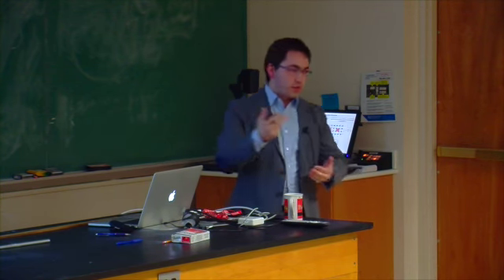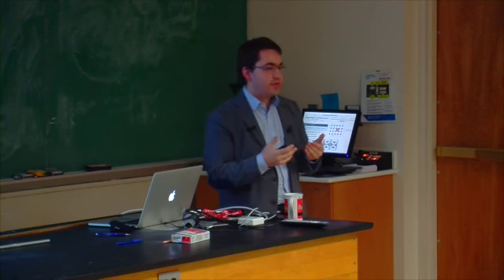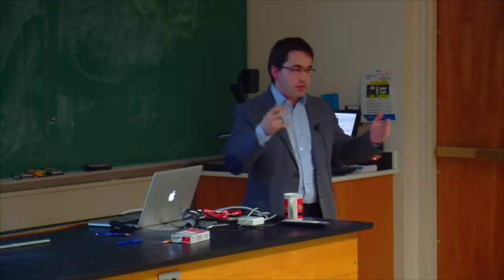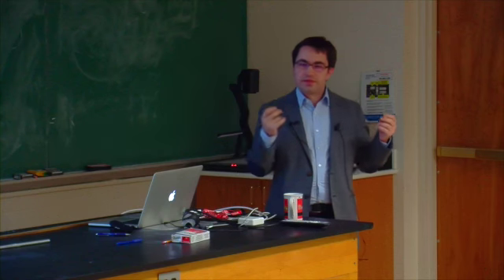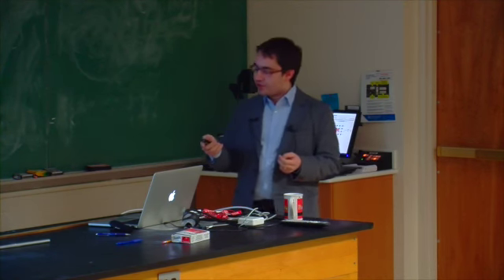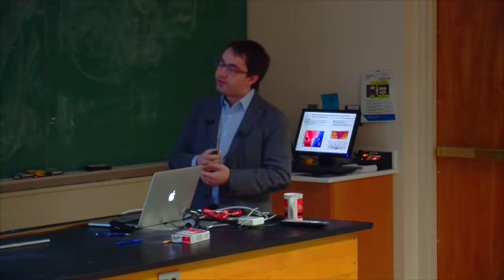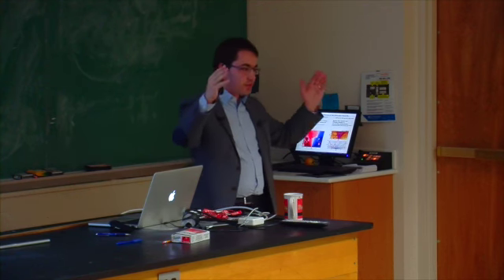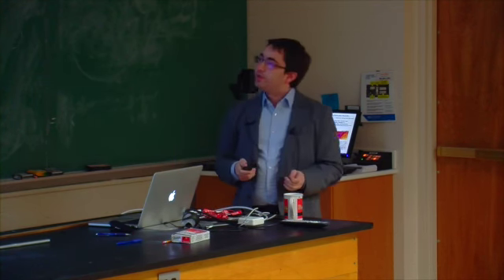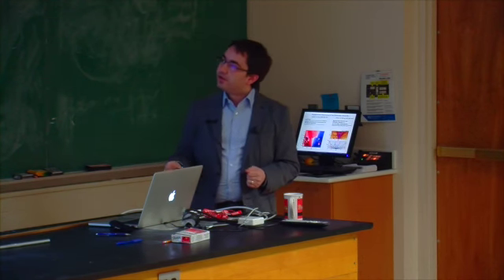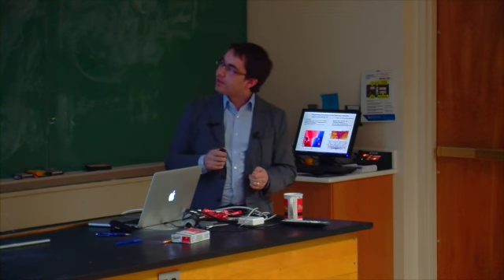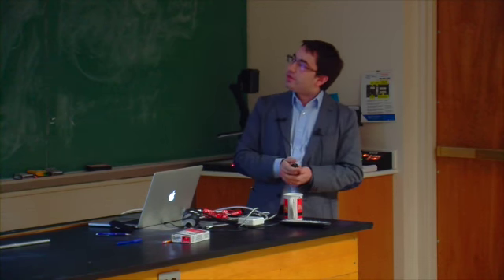So one thing that was tried is to make artificial periodicities, but this never quite worked out because you couldn't get that to be precise enough to get the right results. However, because of this Moiré pattern that introduced this larger periodicity, this Hofstadter butterfly was spotted in 2013, almost simultaneously by the group of Philip Kim and the group of Herrero at MIT, due to the presence of the Moiré superlattice.